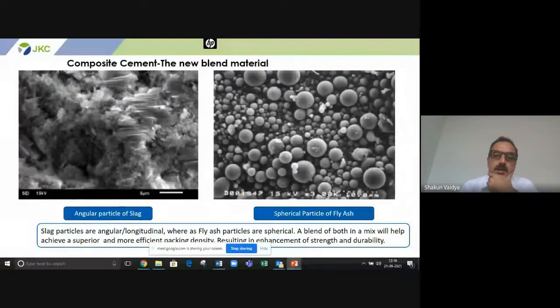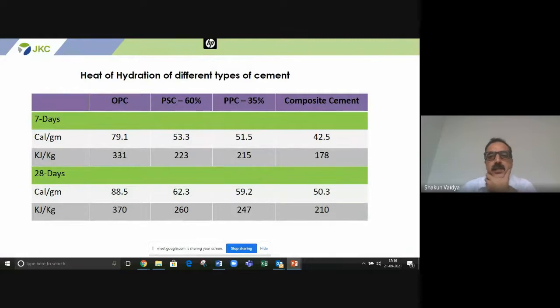Angular particles of slag and spherical particles of fly ash also provide a better packing density. Heat of hydration is also on the lower side. This is a very, very critical requirement, especially in mass concreting works. As you can see, OPC is the maximum. That's the reason this is not considered a very sustainable product now, because more heat of hydration means more formation of capillaries and pores and ultimately pervious concrete.